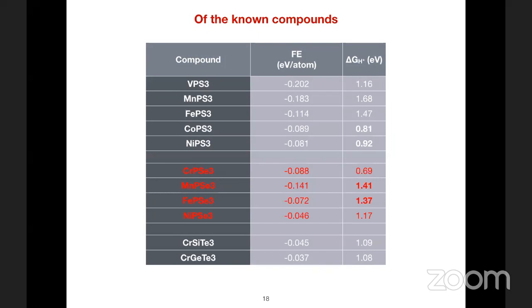Okay, now what about the known compounds? What about iron phosphorus selenide, manganese phosphorus selenide, and the cobalt and nickel sulfides? As it turns out, cobalt and nickel sulfides have the lowest delta Gs among the known sulfides, but they are nowhere close to 0. It's 0.8 and 0.9. On the other hand, manganese and iron selenides turn out to have some of the largest delta G values. So the question is, why this discrepancy with experiments?